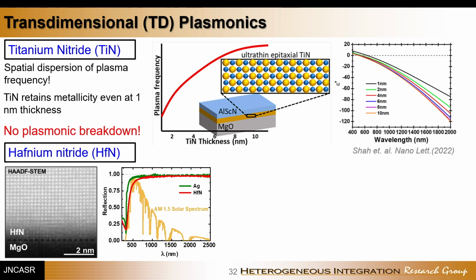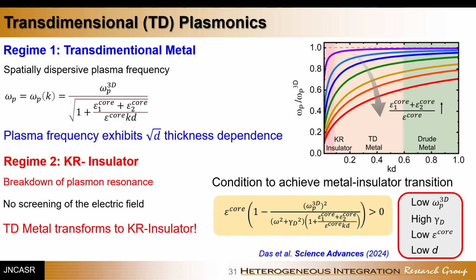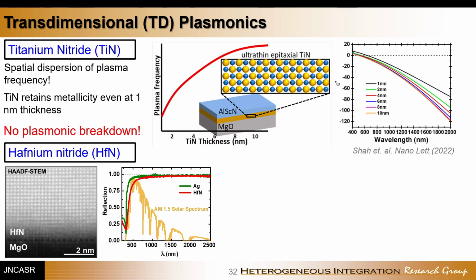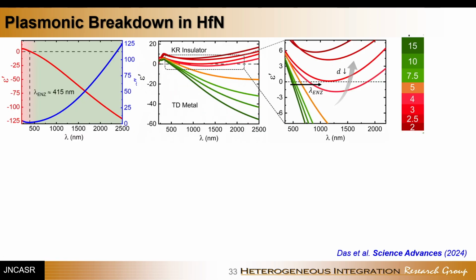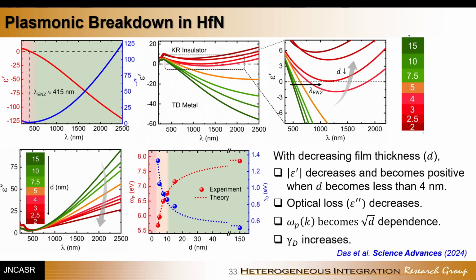So the next thing we tried to look at is what happens with hafnium nitride. As I mentioned in the last slide, to see plasmonic breakdown, one requires a very stringent optical condition. So in the case of hafnium nitride, this is the thick film. As you see, this is the ENZ at around 350, 340 nanometer wavelength. And as you reduce the thickness from 10 nanometer to 2 nanometer, you see there's a progressive reduction in epsilon prime, which is the real component of the dielectric constant, from a negative value to a positive value, essentially underscoring a transition from an optically metallic regime to an optically dielectric regime.